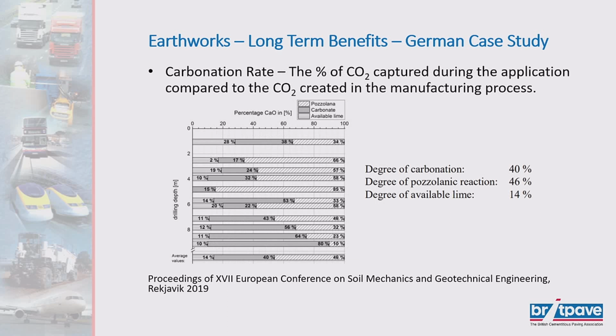I'm going to talk a little bit here about carbonation. Soil stabilisation can get a bit of a bad reputation in terms of the amount of carbon embedded into it. But carbonation rate is the percentage of CO2 that's captured during the application compared to the CO2 created in the manufacturing process. And what this German study found is that over the period of time, there's 40% carbonation. So 40% of the CO2 that was produced in the manufacture has been captured during the life of that product. So it is taking back CO2 within. So the use of lime or cement or other materials within it, the carbon is there, but it is actually going to get some of that carbon back.